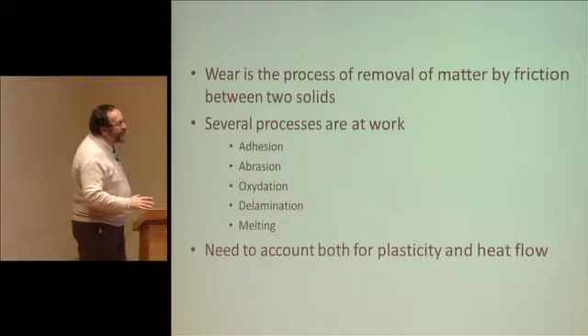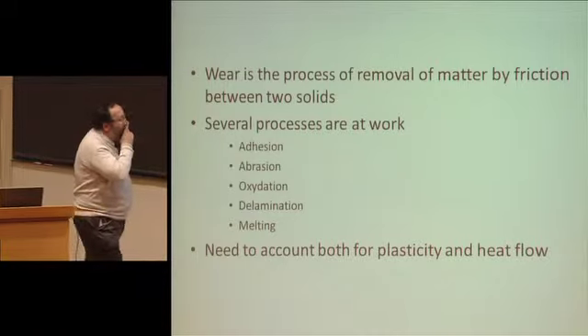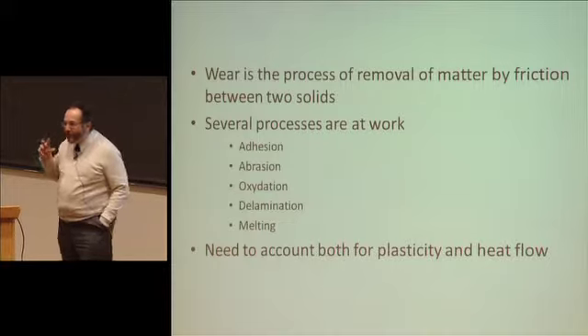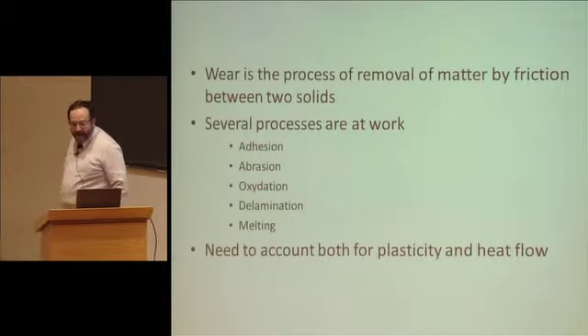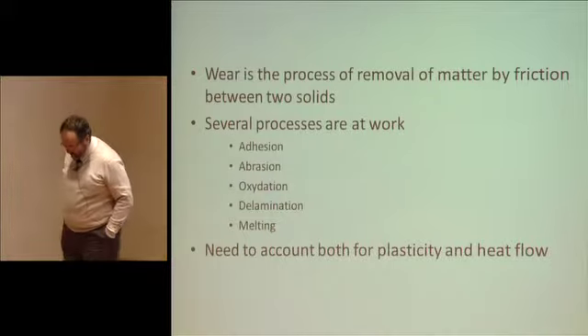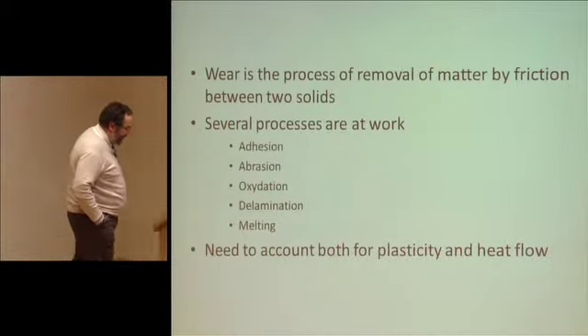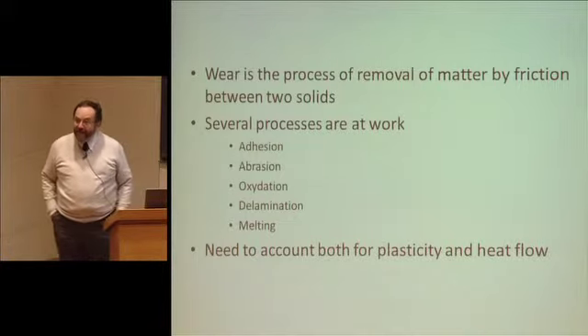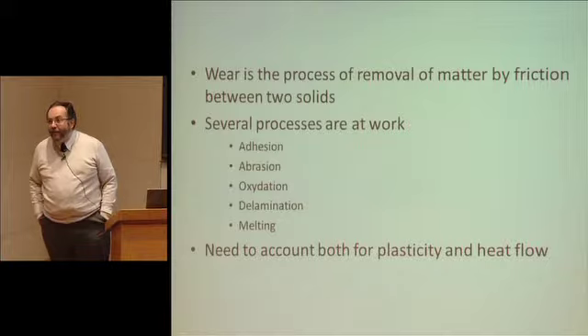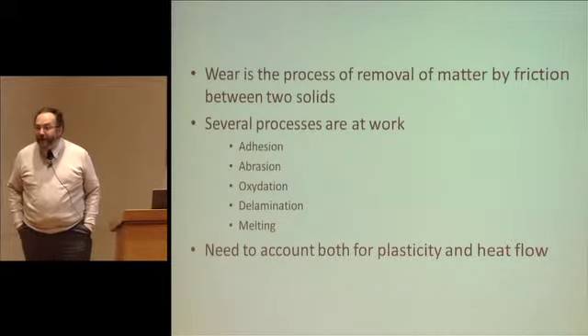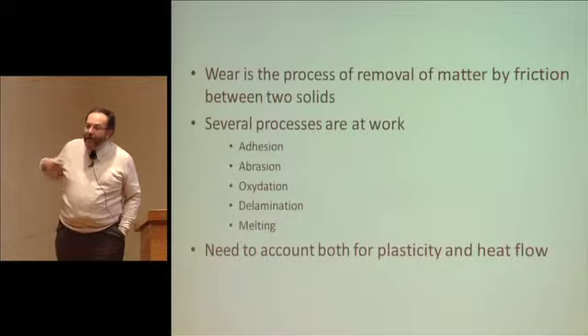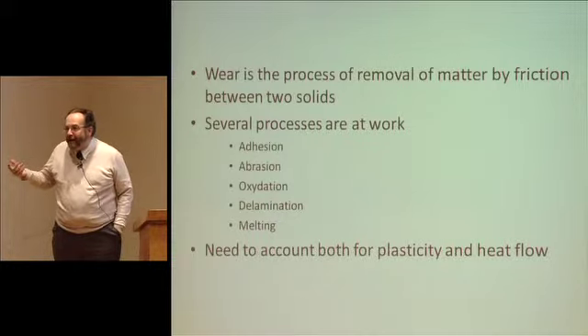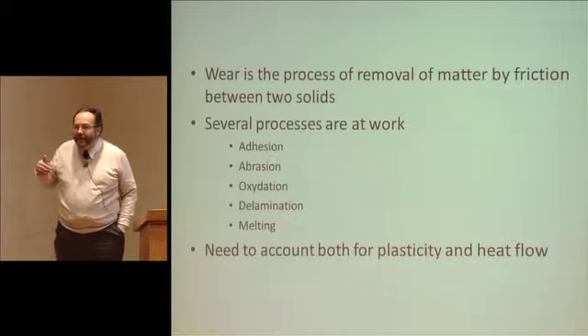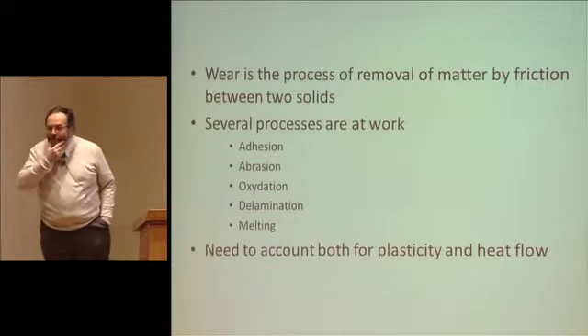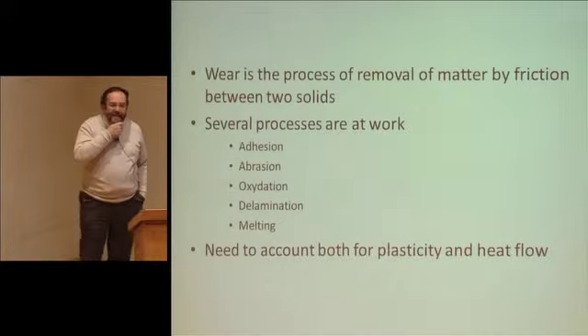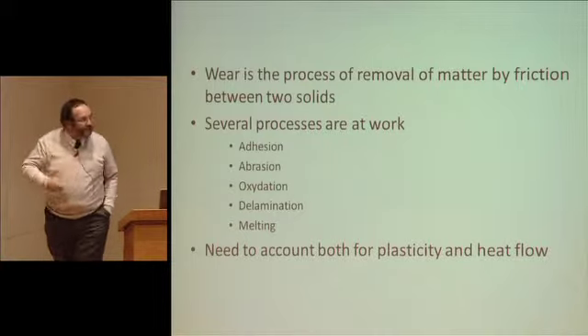If things are happening in an atmosphere that's slightly chemically aggressive, you're sure that you won't understand a thing. But you can always try to see how you can actually envisage the problem to try and gain some understanding. There are several processes at work in wear, in the same way as a certain number of processes active in creep. The difference is that in creep, you have few active processes. So you can have creep maps that are bottom up. You can describe reliable models and then, based on these, try to build creep maps. With wear, things are much more annoying because you can only rationalize empirical maps.